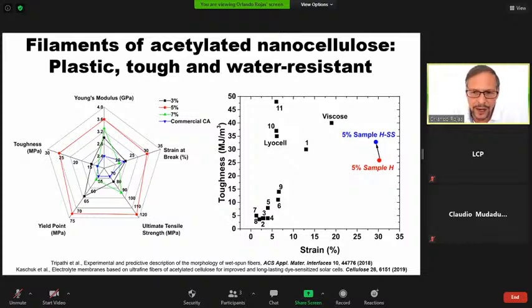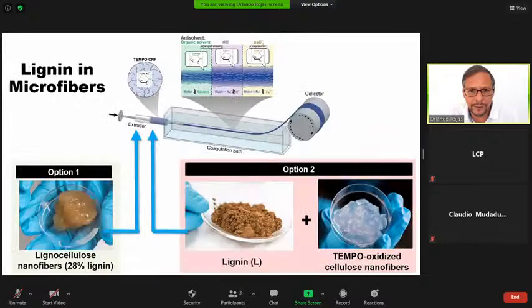You can see here the strain reaching out to 30%, in the range of 30%. And these are the samples in blue. And they are quite competitive if you think about how they compare with other commercial materials. So as far as extensibility, it's quite interesting. But also as far as the water resistance, these materials, these filaments that are produced by acetylated nanocellulose are water resistant.